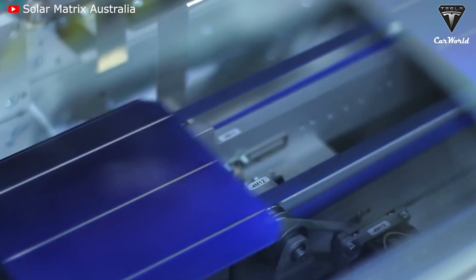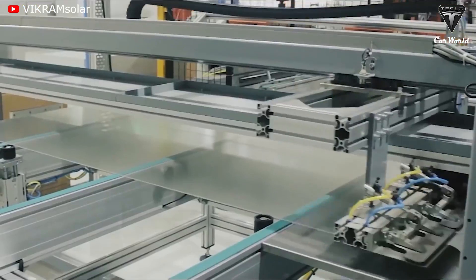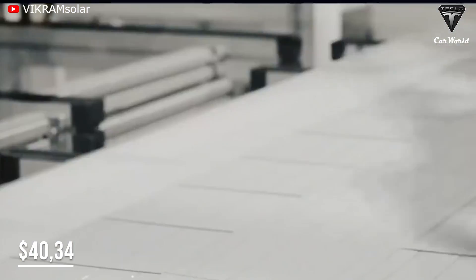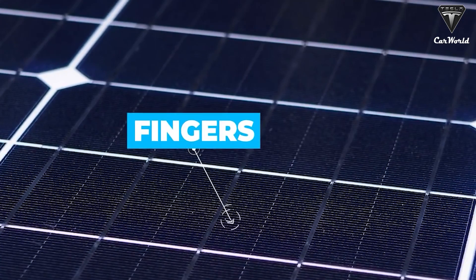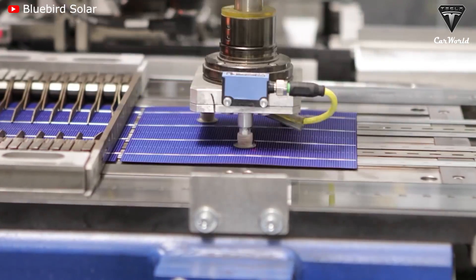Strong demand coupled with production glitches has pushed the price of key materials — mainly polysilicon — for solar panels to the highest level. The cost of the most expensive grade of polysilicon rose to $40.62 per kilogram, surpassing last year's high of $40.34. Polysilicon makers take 99% pure silicon metal and remove impurities until it is 99.9999% pure. As the silicon rods are forming at the center of the reactor, the walls need to be kept cool to prevent silicon from crystallizing there. Maintaining that temperature difference is really energy intensive.